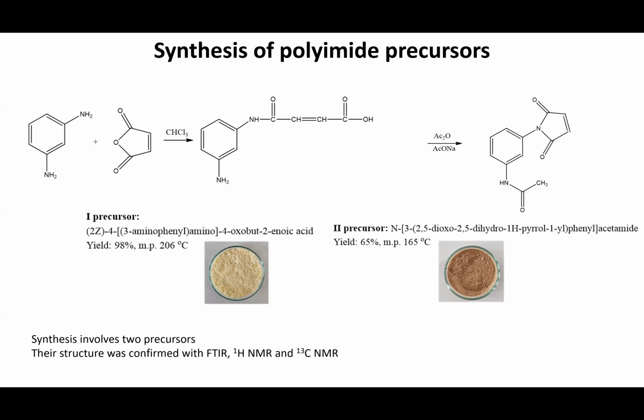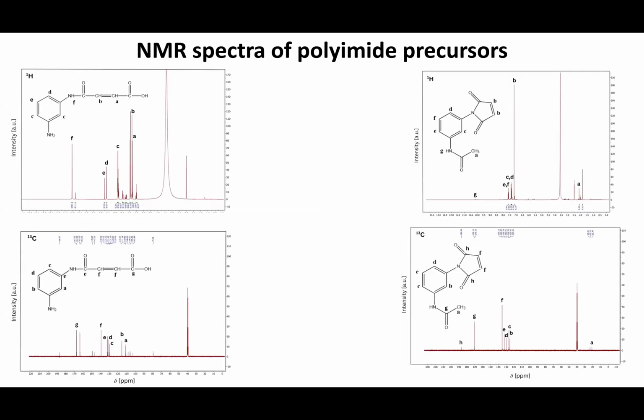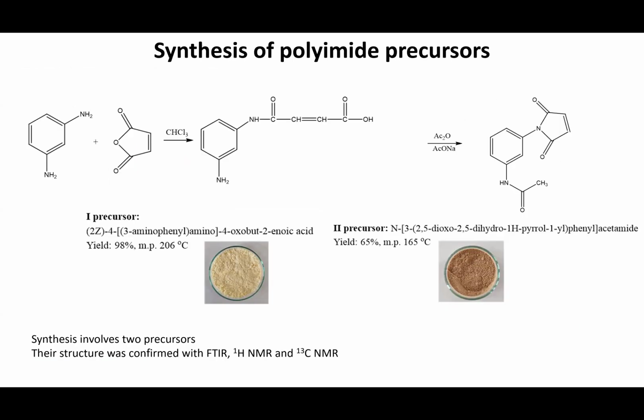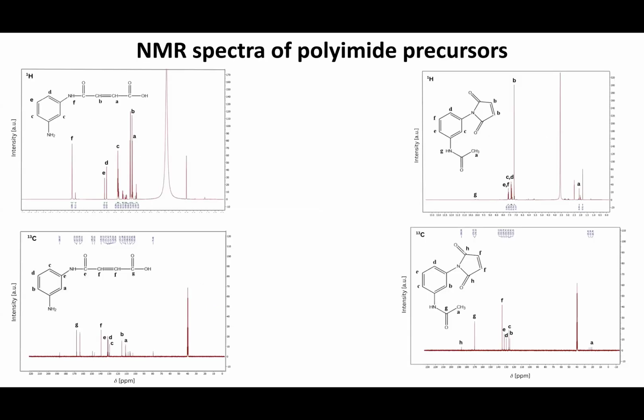So I will show you, this is the most complex synthesis that we did. It contains 3 phases. You have 2 precursors shown on this slide here. We synthesize the first precursor shown in the top middle, and then from that, we synthesize the second precursor shown in the top right. And then from that, we can attach different crosslinkers to the end of the second precursor and get the final product, which is the polyimide. During these middle steps, we performed NMR and FTIR, and I will show NMR spectra of these polyimide precursors. You can very clearly identify the bonds here. It matches perfectly, and we know that we've done our synthesis well, so that we can track our chemistry through this synthesis process.